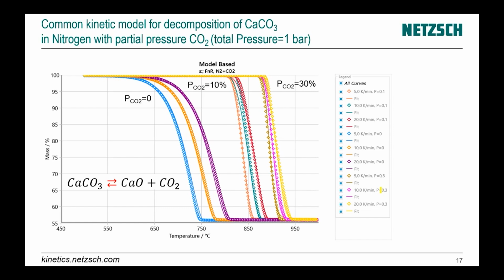And now our data. We have firstly pure nitrogen, and the partial pressure of CO2 is 0. We have 3 curves with 5, 10, 20 K per minute. Then we have partial pressure of CO2 10%. We have again 3 experimental curves, 5, 10, and 20 K per minute, and the third 3 curves are done for 30% of the partial pressure of carbon dioxide.